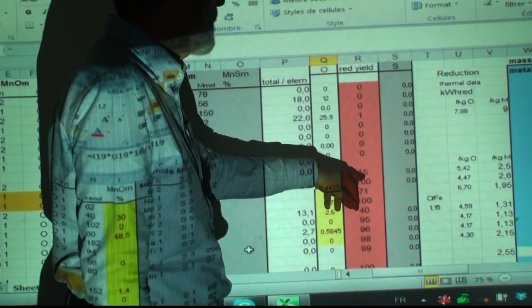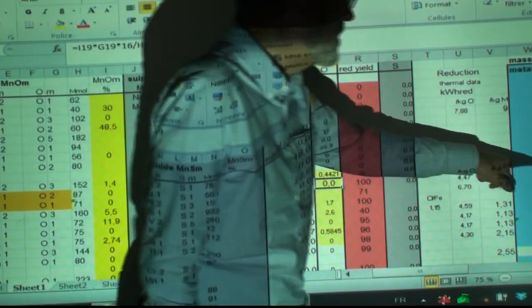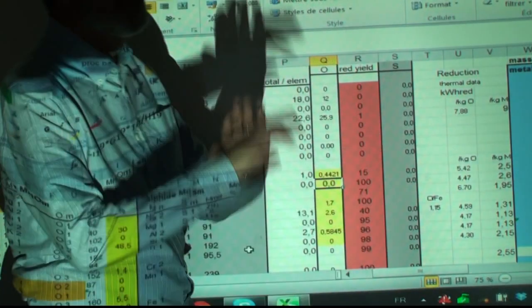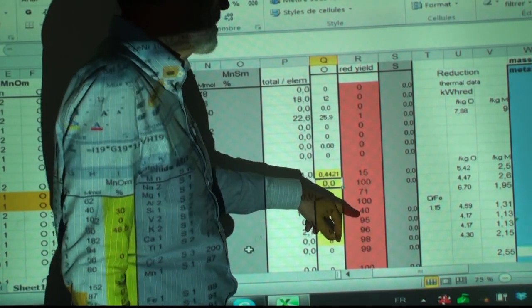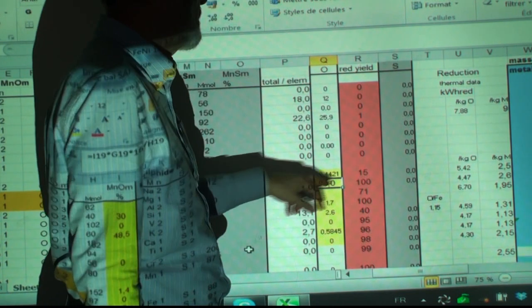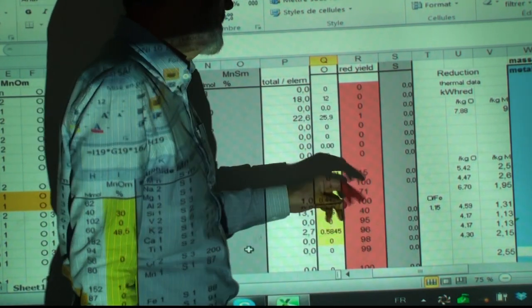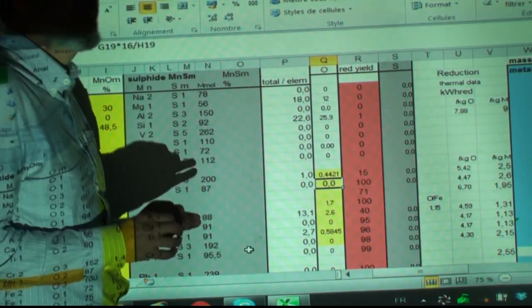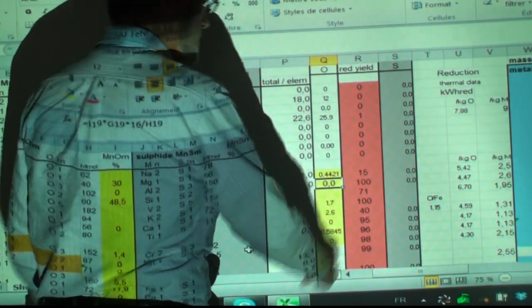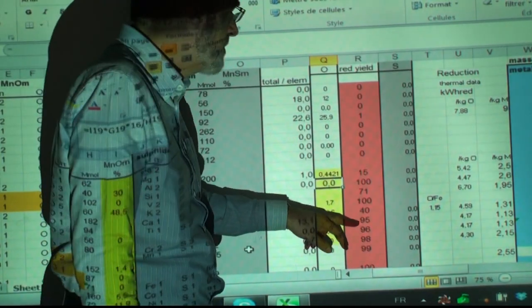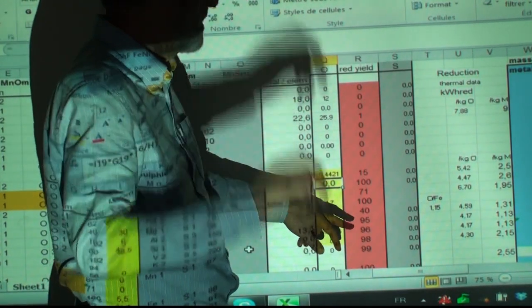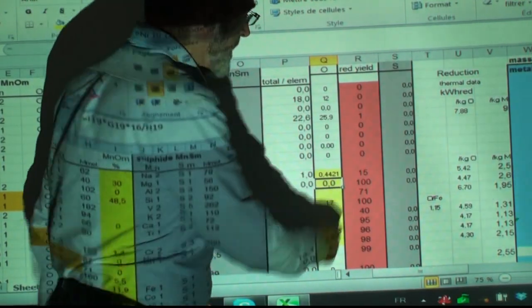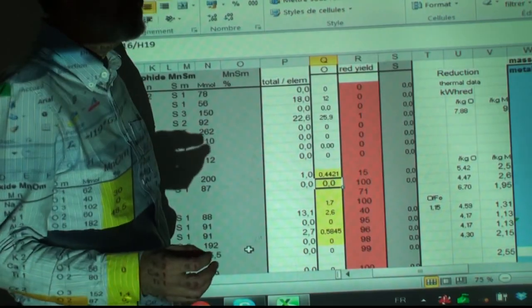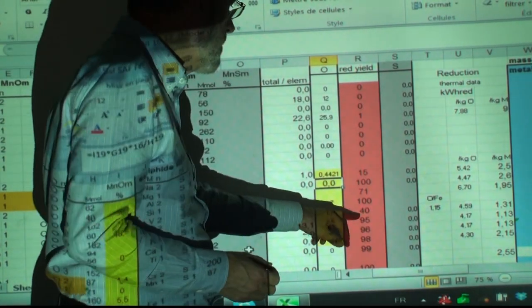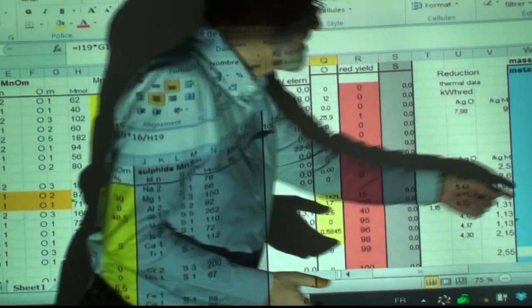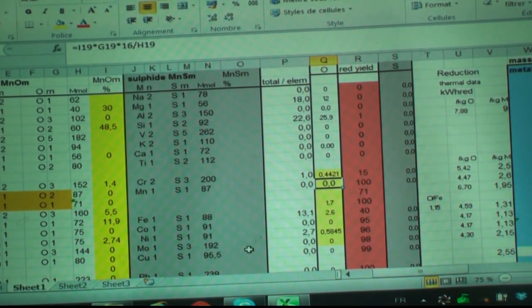You see, if we have 30% instead of 15, we change 0.1 to 0.2. You can forget this. What is important? Nickel. Here you must have a good nickel yield, at least 95%. The other adjustment parameter is the yield of iron. The yield of iron can be 40 or it can be 60. What you must check is the result that you have.